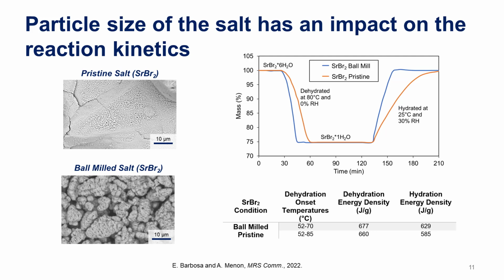And that directly ties in to the energy density itself. You can see our ball milled salts have energy densities over 600 joules per gram, whereas for the pristine salt, it's lower. And for some of our other salts, we see even bigger contrasts with and without ball milling. That really emphasizes the importance of understanding how the microstructure of the salt impacts the properties.